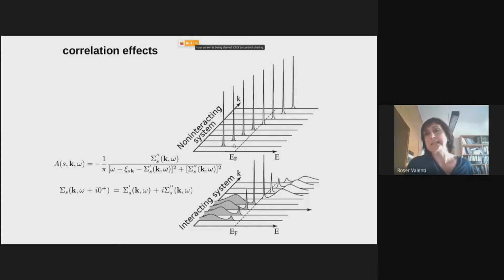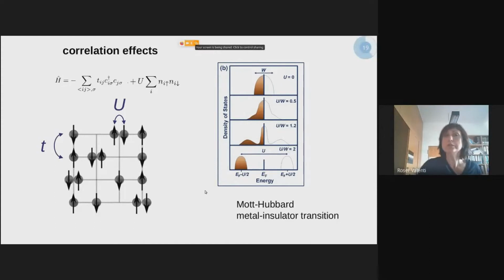And what happens then is that the particles have a finite lifetime, and there is a transfer of spectral weight to what we call the lower and the upper Hubbard band. And this, in fact, is influencing the properties of the system. So we need to have methods to describe these effects which are not captured in, for instance, DFT. And just to show you how to include these effects, in the Hubbard model, because you explicitly take into account this Coulomb repulsion, one can describe what I was telling you, the effect of this transfer of spectral weight due to the Coulomb repulsion among the particles.